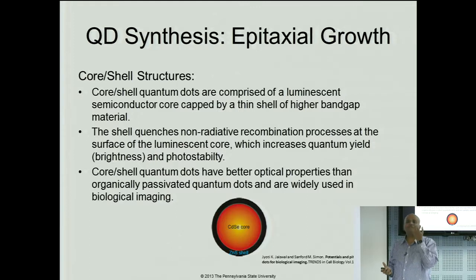That is the reason whenever you do an optics experiment, or if you have done it in your high school or any time, you do it in a dark room. So, this is basically the effect of doing it in a dark room. So, you are getting more intensity, but you can't overdo it. This coating is 2 nanometers. You cannot put a 5 nanometers coating on top of it, because then you would be losing the properties of the quantum dots.